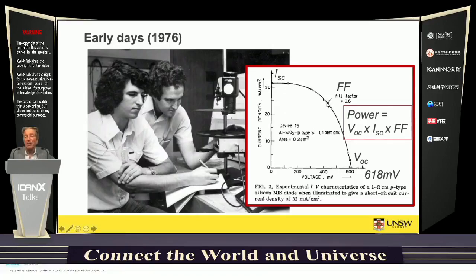That's shown where the dot is on this particular curve, and then it reduces again as you go towards the open circuit voltage. So you get maximum power around here. So you can express the power as a product of the open circuit voltage, the short circuit current, and what's called the fill factor. In this case, a very lousy one of about 0.6 or 60%.